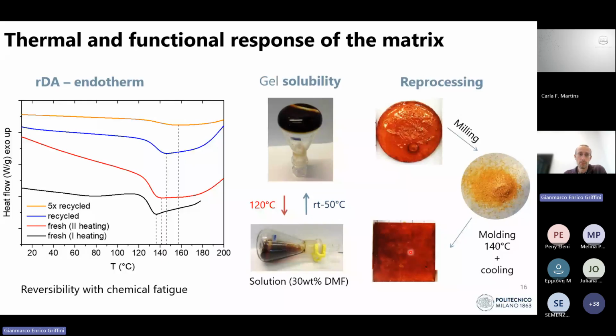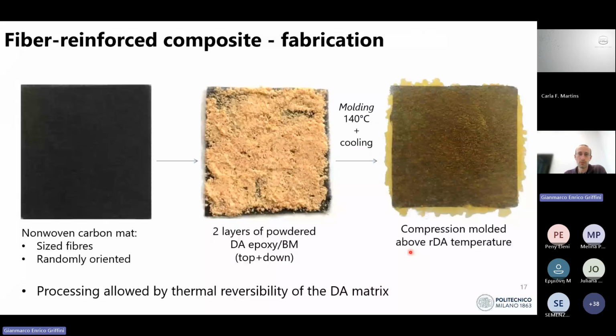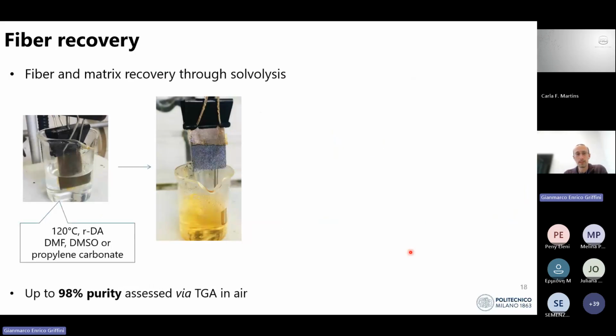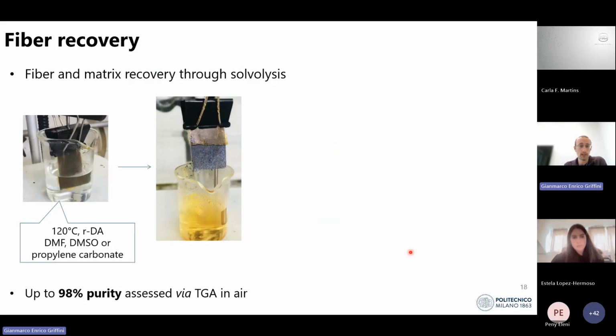Given these properties, we then decided to incorporate that resin as an impregnating resin for a one or two layer composite material to demonstrate the feasibility of the concept. Once the material was obtained, we evaluated the possibility of recycling the material itself, so dissolve the resin at high temperature, recover the fibers, and potentially reuse the matrix itself. So you see here that the solution was successful.